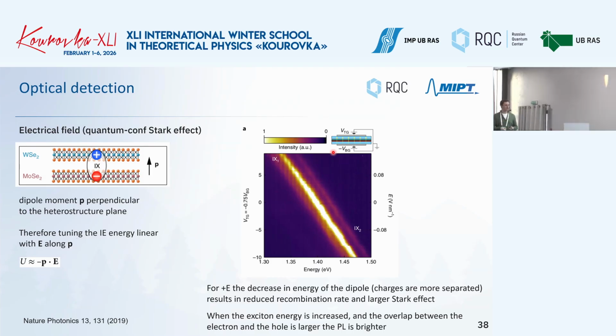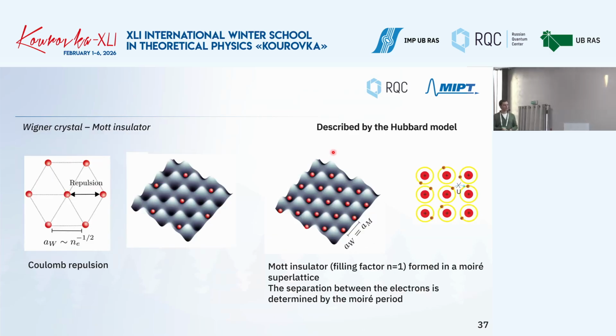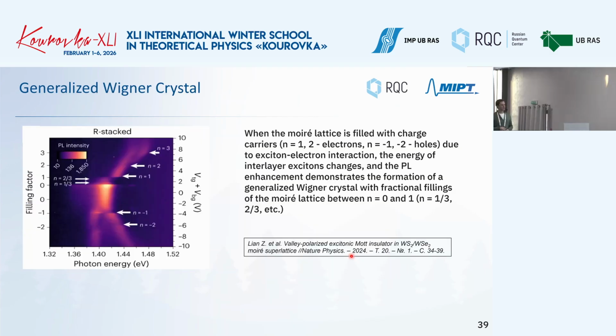For example, if you have a Wigner crystal case here, when you probe, you measure your interlayer excitons. Depending on whether your system is in this case or in this case, the interlayer exciton will feel this difference of the reconstruction of the crystal structure. And then this interlayer exciton will serve you as a guide, just to prove that something has happened. With this detection of the interlayer excitons, one can claim, okay, I have a different filling factor, I have a different state, and maybe it can be described as a Mott insulator, or maybe as a Wigner crystal. And this is exactly what people published, for example, in 2024 in Nature Physics.